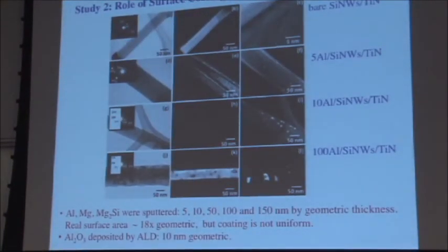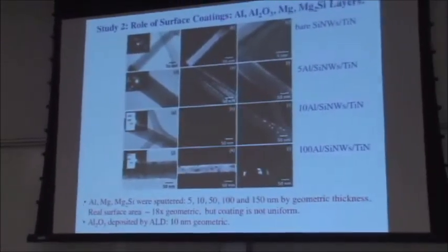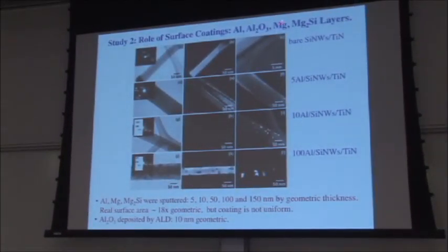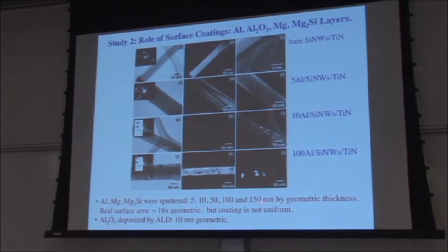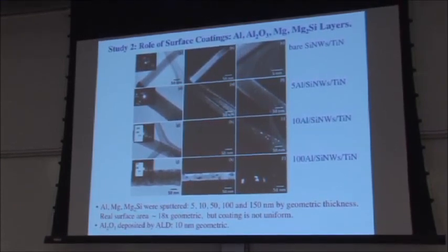So now what we started doing is looking at the role of surface coatings. And we looked at aluminum, aluminum oxide, magnesium, and magnesium silicide layers. And these were sputtered at 5, 10, 50, 100, 150 nanometers by geometrical thickness. The real surface area is 18 times the geometric, but the coating is not uniform. So don't take the numbers I'm going to quote as exact. This is sputtered deposition onto a non-vertically aligned array, right? So you're going to get a significant amount of shadowing, and you will, to some extent, penetrate near the base,